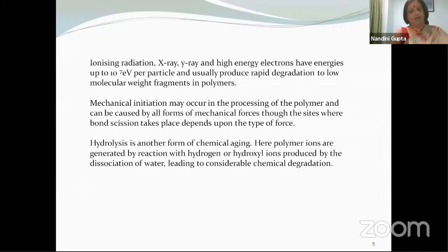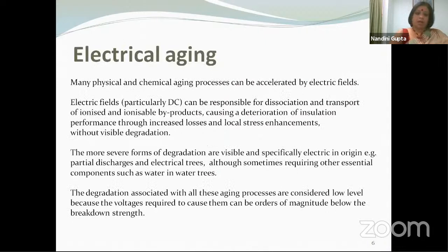In fact, when we work with nanodielectrics, we have seen that the presence of hydrolysis and the presence of OH bonds on the nanoparticle surface drives the properties of the nanodielectrics that we prepare, unless we functionalize the nanoparticles and take care of the hydrogen molecules or the OH ions on the surface. So these are the two broad overviews about aging. Aging can be physical or chemical, and both physical as well as chemical aging can be driven by electrical stresses, apart from other mechanical and thermal stresses. So that is the point.